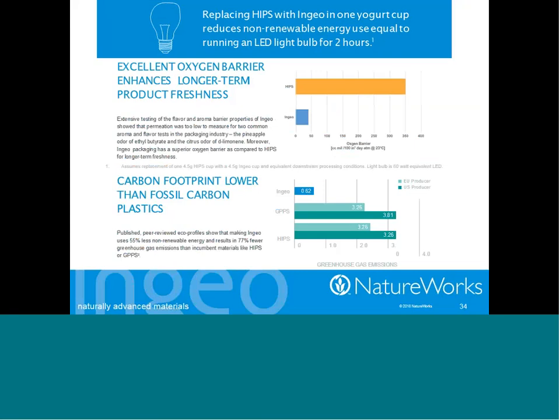And there's yet another benefit to PLA that's again inherent to the material, and that has to do with the natural O2 barrier and flavor and aroma capture within the packaging. So shown here, the top one is the oxygen barrier. You can see it is much lower for Ingeo, or for PLA, compared to polystyrene. That leads to longer shelf lives. The lower aroma thresholds keep the flavor in the food and the smell out of the refrigerator.